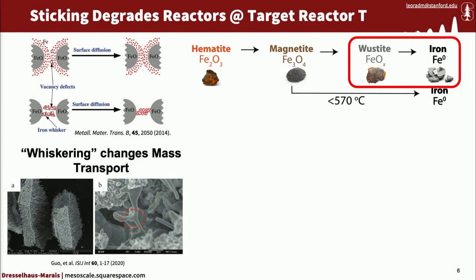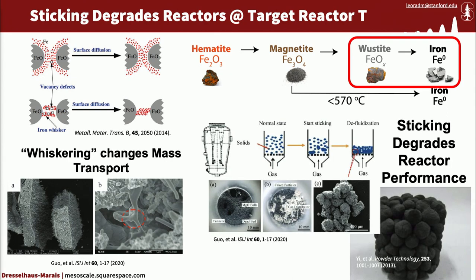This is called the sticking or whiskering mechanism, by which, as you convert from your iron oxide to your metallic iron phase, the transport of iron ends up bridging particles that are near each other, causing them to whisker and stick together. Therefore, in a reactor, either a fluidized bed reactor, which is one approach to scale this process, or a blast furnace and pellet-based reactor, which is a different version of the process, in both cases it causes these sticking effects that ultimately prevent the reactor from continuing and cause catastrophic failure that then requires you to close down the reactor, clean everything up, and restart the problem.